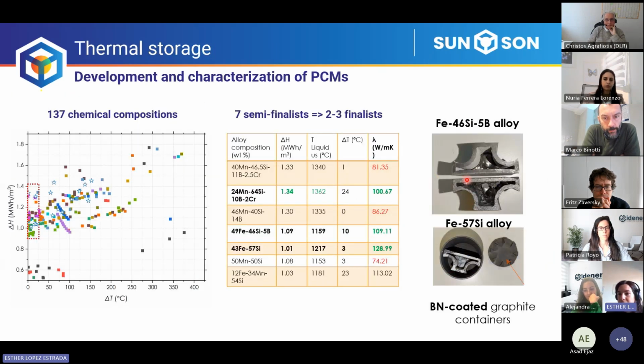Here in this slide, you can see the specific shape of the crucibles that will contain the PCM. And as I mentioned before, this PCM is the element that stores the energy. In this project, we have studied different alloys, first of all theoretically using simulations to predict which ones can be the most promising as PCM. And afterwards, we have fabricated and tested some of them to check the empirical value of the main parameters, like, for example, the energy density that can be stored, the melting temperature, and also the conductivity of the PCM. It's important to have a high conductivity in order to transfer the heat effectively.